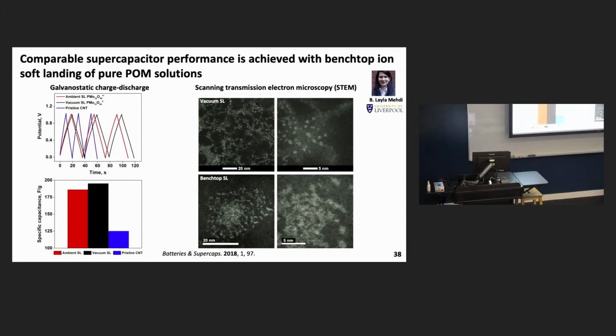I mean, it's probably within the error, right? And in fact, the specific capacitance as well is very similar. So we wanted to see at a molecular level, is the dispersion of these materials on the surface the same? Is it different? What is responsible for this activity? In the case of vacuum soft-landed polyoxometalates, you see this spidery distribution of ions on the surface, and you can actually make out individual atoms comprising those clusters.